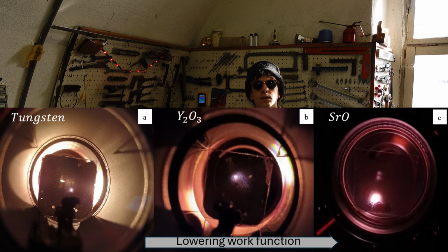The intensity of the fluorescent screen light is proportional to the current carried by the electron beam at the same potential. On the left we have the bare tungsten wire, and then an yttrium oxide coated cathode. And then finally you can clearly see a higher emission from the strontium one.